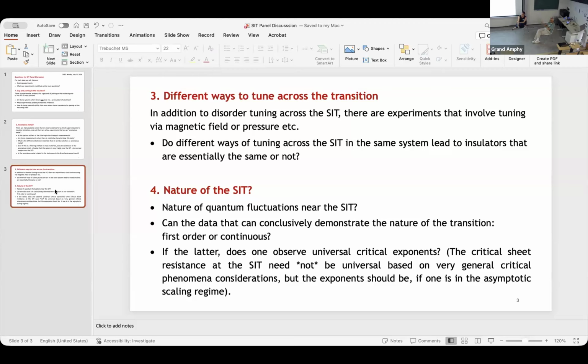So if you have a metallic plate above, that can also change the problem. Any experiments in this direction? Yes, the superconducting screening gate will influence screening lengths. It will not only affect thinning, but also the pinning of vortices. It's different when you tune past the transition. So I'm proposing.